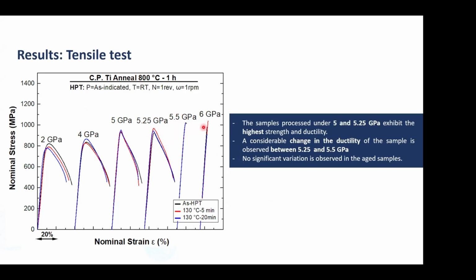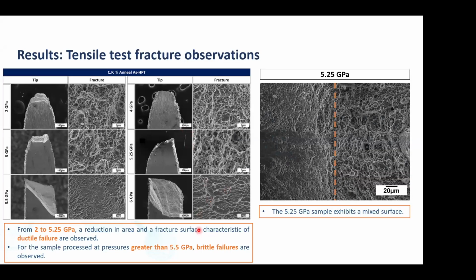So it is interesting to see that somewhere between 5.25 and 5.5, we see the loss of ductility. The hardness or the strength keeps increasing. It seems to be getting to a saturation somewhere around 1,000 megapascals, which is great hardness, great strength for a titanium alloy, but ductility is the issue. So we can tailor, as I said, and we are investigating which heat treatment condition gives what kind of properties. If we look at fracture surfaces, it's interesting that at some point the fraction of omega phase makes the failure mode change from ductile to brittle, and we're looking into investigating that a little bit deeper.